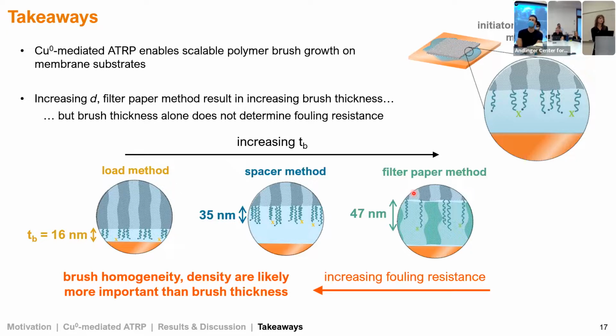that's resulting in lower fouling resistance. And in terms of the zwitterionic layer, potentially a more dense layer, even if it's thinner, might give us a stronger hydration layer, which gives us better resistance to attachment, and better steric hindrance with the brushes. So that's my guess, but we are looking into characterizing density right now. It's a little bit tricky.